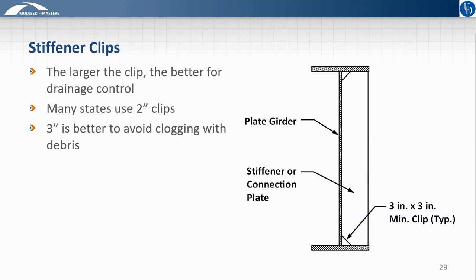So that was for haunch girders, but of course, even for constant depth girders, you have often transverse stiffeners that are welded on. And these require clips at the bottom to prevent this debris from building up and to allow drainage along the flange length. Many states use a 2-inch clip as their standard. That's sort of a minimal clip size, in our opinion. 3 inches is better. If you get even larger than that, that's great. One common practice is the pop or soda can test. If a soda can pass through it, then it's big enough. And that's a good rule of thumb for any portion of a drainage system design.